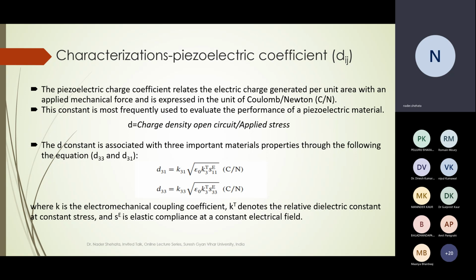It depends, of course. Each D depends on other material-dependent parameters, including the electromechanical coupling coefficient, the dielectric constant, and the elastic compliance, or the mechanical effect, and it's preferred to calculate it at a constant electric field. Here, the most important and most used parameter to check whether the material has high or lower piezoelectric performance is D33.